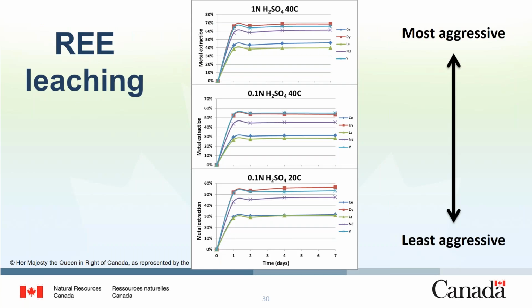Here we have the results of the leaching test with 1 of the fly ash samples with sulfuric acid. The 3 graphs are ordered from the most aggressive conditions on top to the least aggressive conditions on the bottom. As you see, the majority of the leaching occurs within the first day. There are 2 interesting trends. The first is that the process is relatively insensitive to both acid concentration and temperature over the range tested. And the second interesting trend is preferential leaching of the heavier elements, so we're actually getting fractionation as we're leaching.